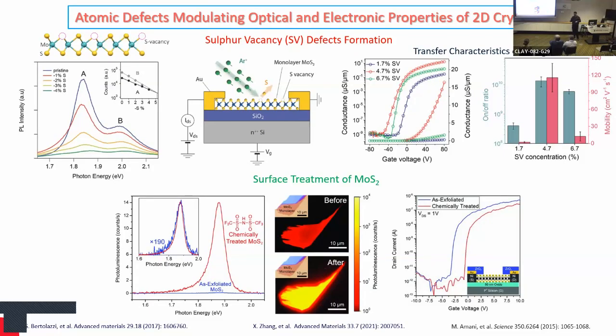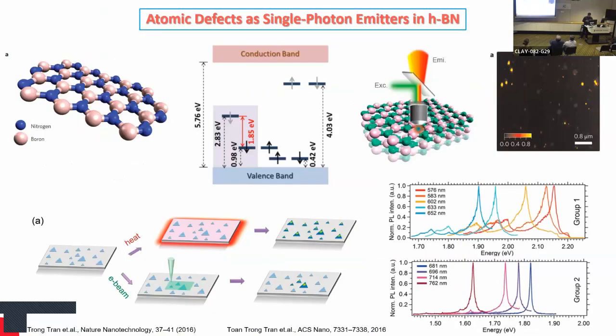For example, if you have some surface defects, you can do some chemical treatment. It will restore the surface again, and your properties will be restored again. So this is very interesting because you have just one layer of material, so it can be easily manipulated using different techniques of defect formation and also passivation. Another very common defect system is in boron nitride. It is used because boron nitride is a wide bandgap 2D material, so we can have some in-gap states which can act as quantum emitters. Many papers have been published in this field as well.